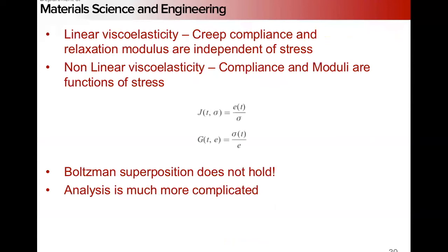Okay, so we have a couple slides that we're going to wrap up on Wednesday on nonlinear viscoelasticity, right? And remember, so in linear, we said the compliance and the modulus are independent of the stress. For nonlinear viscoelasticity, the compliance, creep compliance, and stress relaxation modulus become explicit functions of the stress. So if we increase our stress, we're going to change our moduli values. So that means our Boltzmann superposition doesn't hold, and all of the analysis becomes really nasty really quickly.